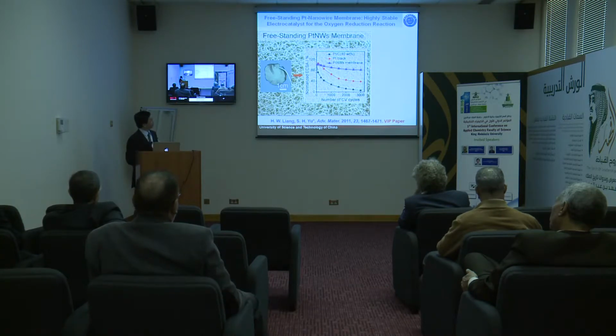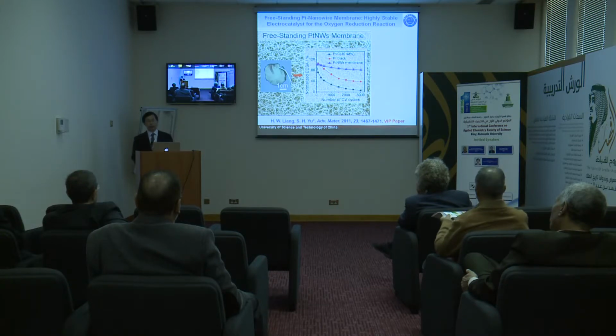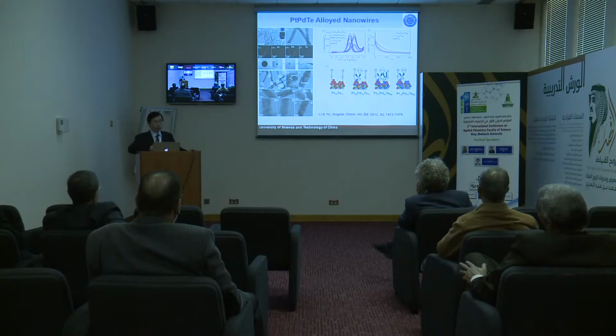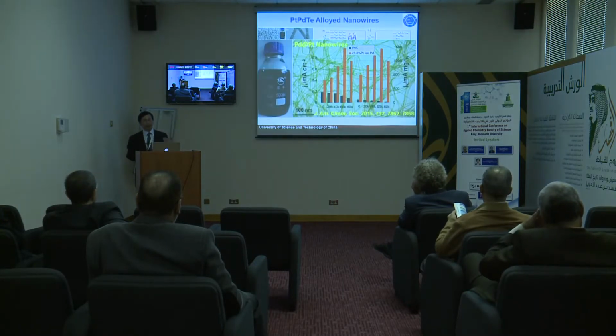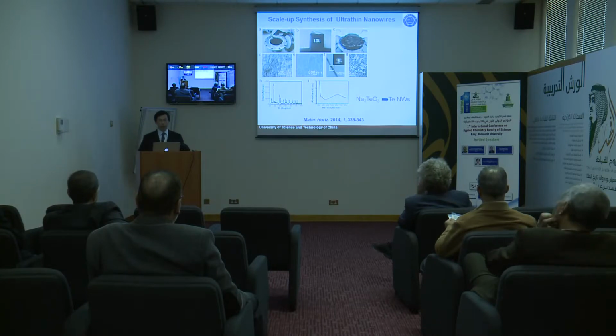And we studied their electrocatalytic performance for the oxygen reduction reaction. The result shows that indeed you can improve it. You can find that the nanowire network is good. They show good stability for the oxygen reduction reaction after many CV cycles. Another way, you can get new alloyed nanowires. You can tune the composition so that you can optimize the electrocatalytic performance of this alloyed nanowire system. You can even coat very thin layers on the surface of the nanowires so that you can further engineer their electrocatalytic performance. So there are many ways for you to synthesize new nanowires.